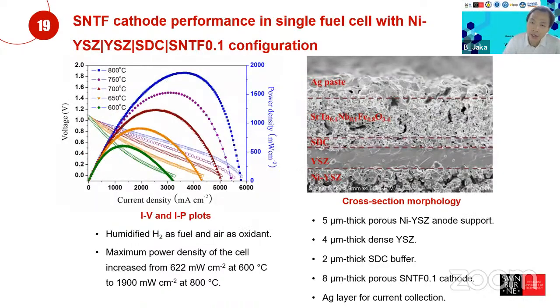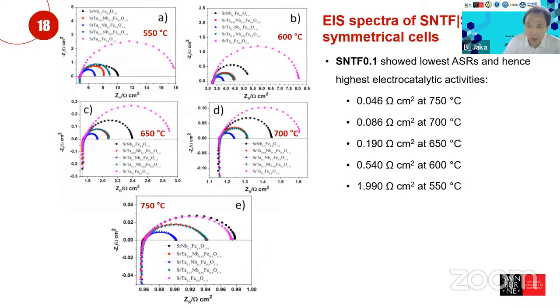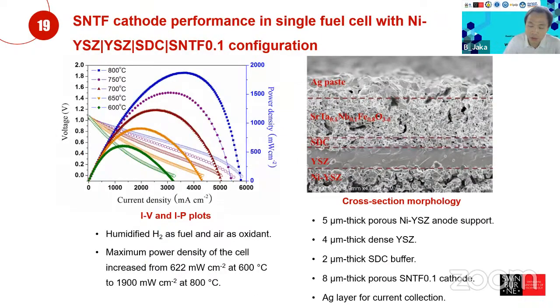And we also make another one. The one that we did in here is what we call a symmetrical cell. The one that we call in here is a full cell. Full cell means that we put in the electrolyte, we attach a cathode, and we attach an anode. And then we put hydrogen into the anode side, and we expose the cathode side to the air, and then we start the polarization experiments. Okay, we carry out from 600 to 800 degrees Celsius, and we find that the maximum power density increased from 622 at 600 degrees Celsius to 1900 at 800 degrees Celsius, which is quite good.